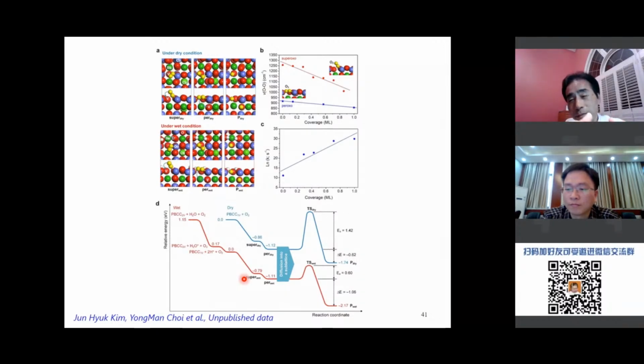So locally, if the steam to carbon ratio is high, then you will no longer have coking. For a lot of catalysts, the first most important property is that they have to adsorb a lot of water on the surface. That way, once you can maintain a certain concentration or surface coverage of water on the surface of your electrode, then you will be safe.